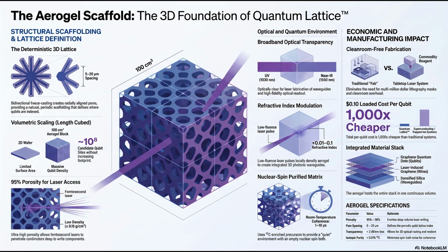The paper says this 100 cubic centimeter block has a porosity of 95 to 98% and a density of less than 0.15 grams per cubic centimeter. Which means, practically speaking, it is essentially 95 to 98% empty space. It is a solid object that is almost entirely composed of nothing. And that emptiness is the feature, right? Not the bug. Because it's mostly nothing, light can travel through it. It provides the optical access we need for our lasers to penetrate several centimeters deep into the block. Yes, it solves the shadow problem the trapped ions had.